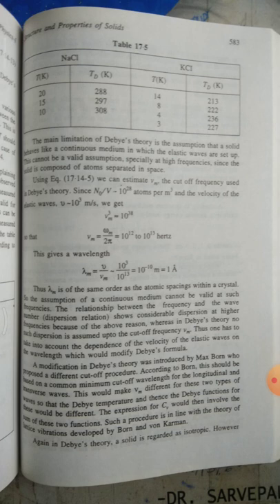hertz. This gives a wavelength λm equal to v by νm, approximately 10 to the power 3 by 10 to the power 13, which is equal to 10 to the minus 10 meter, equal to 1 angstrom. Thus, λm is of the same order as the atomic spacing within a crystal, so the assumption of a continuous medium cannot be valid at such frequencies.